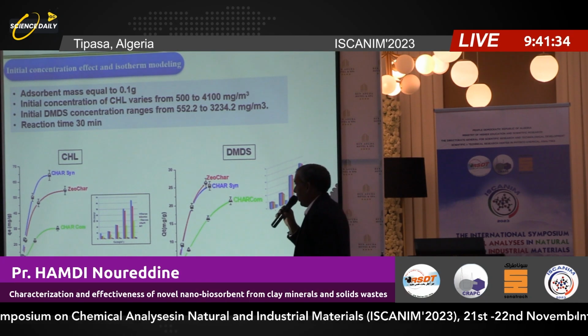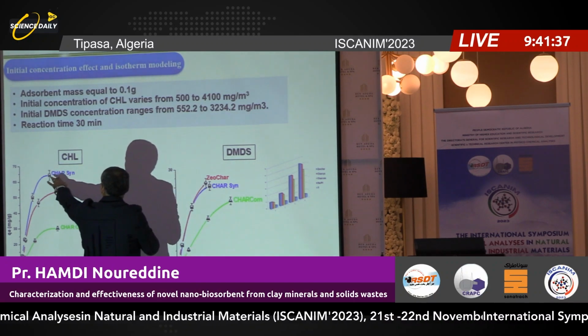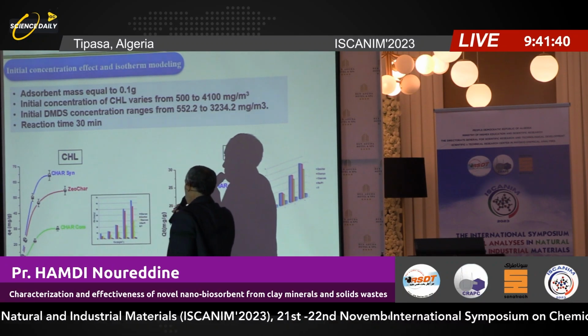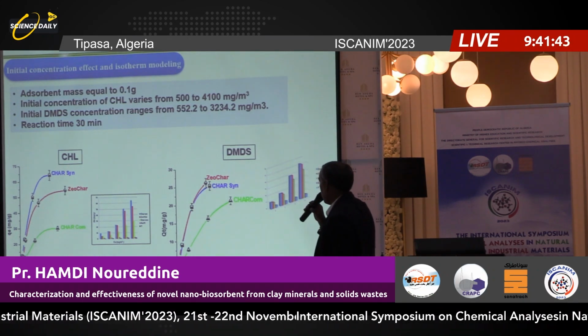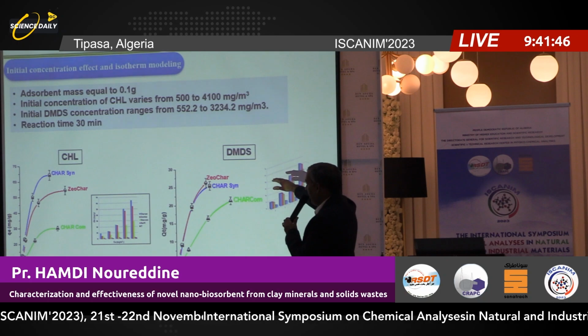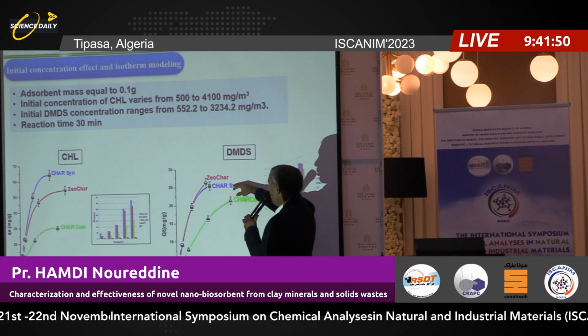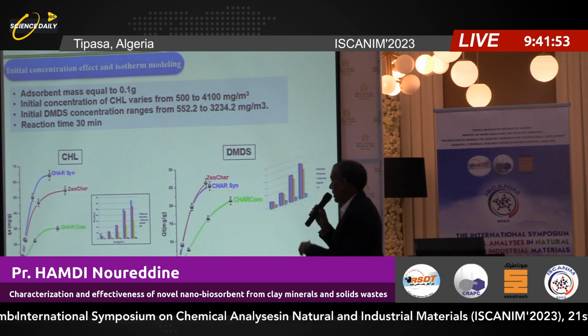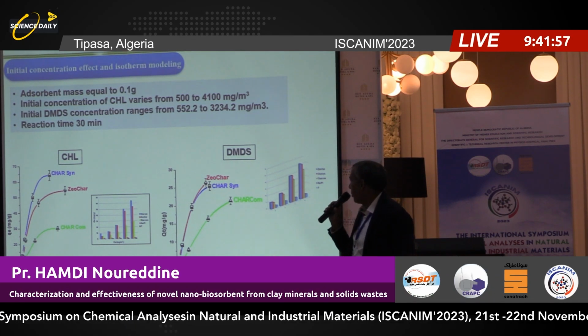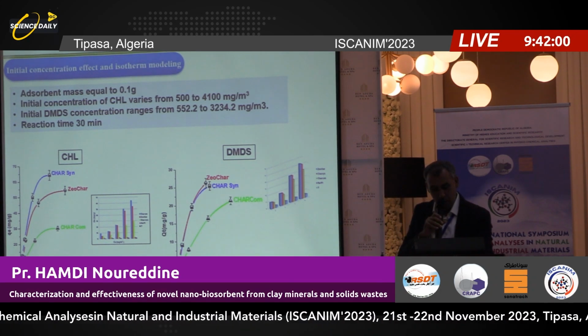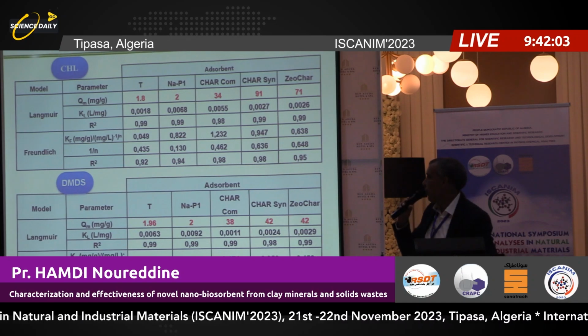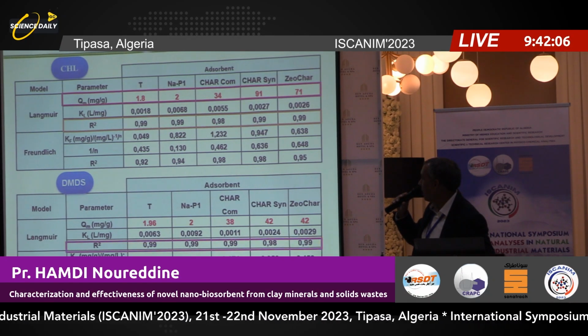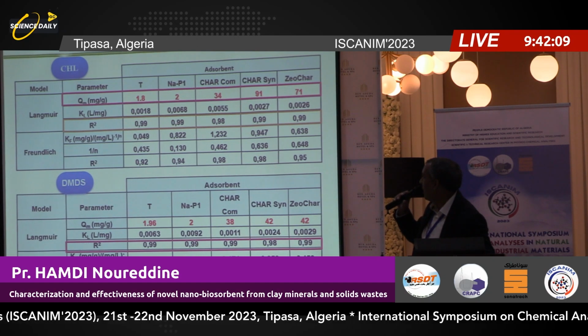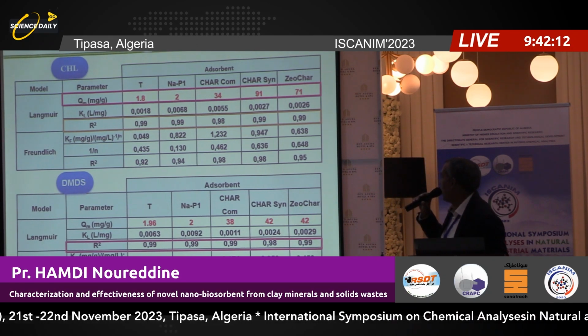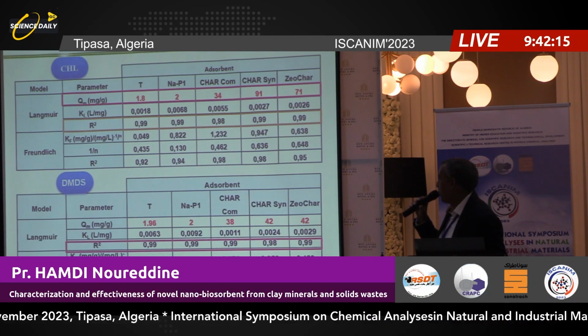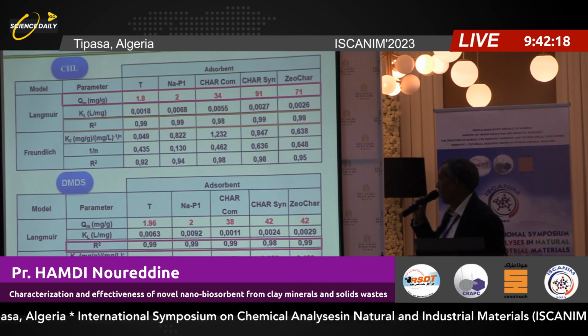We observe that the adsorbed quantity is very much higher for the synthesized carbon, and after that for the composite zeolite activated carbon. The same in the case of DMDS, but here we have the same adsorption quantity for the synthesized zeolite and the composite zeolite activated carbon. Here is the modelization using both models, Langmuir and Freundlich. Langmuir is the best, and the quantity is multiplied by more than 20 for chloroform, and by more than 10 in the case of DMDS.